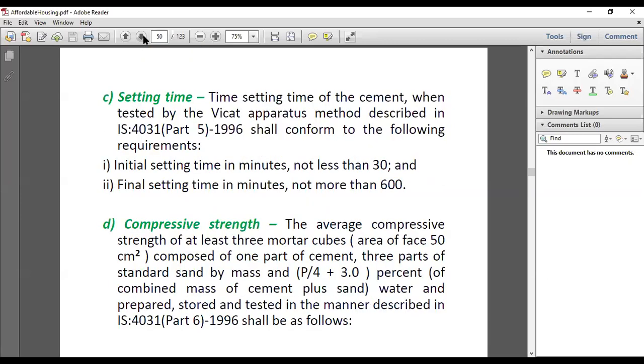Other tests, your setting time. So both initial and final setting time has to be tested. Many times cement doesn't set because they have adulterated it with fly ash. So it is not setting, and when you remove the prop, the whole slab is coming down. So this is the problem of setting time. So this has to be tested.